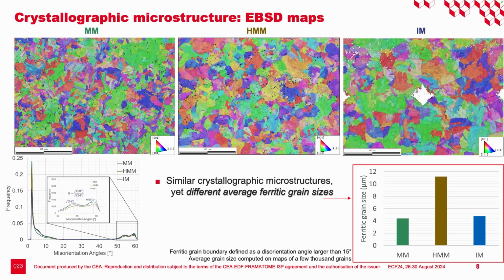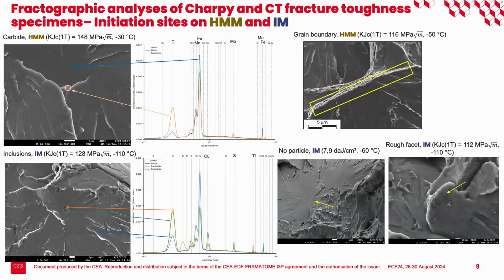And this is the key microstructural element that we need to introduce into the modeling. We have also performed a lot of thorough fractographic exams in the brittle domain, both in Charpy and CT specimens, for the HMM material and IM material. Almost every time, we found only cleavage initiation and propagation, no major intergranular fracture surfaces. And the initiation of cleavage was quasi always on the grain boundaries.